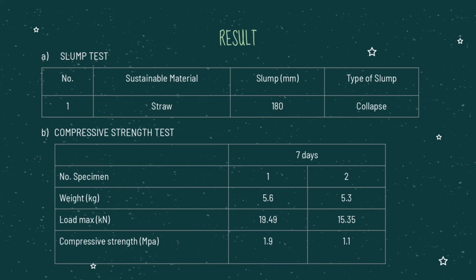The result for the compressive strength test after 7 days of conducting the experiment: we made 2 specimens, which we name specimen 1 and specimen 2. The weight for specimen 1 after 7 days is 5.6 kg, and specimen 2 after 7 days is 5.3 kg. The maximum load for specimen 1 is 19.49 kN, and specimen 2 is 15.35 kN after 7 days. The compressive strength for specimen 1 is 1.9 MPa, and the second specimen is 1.1 MPa.